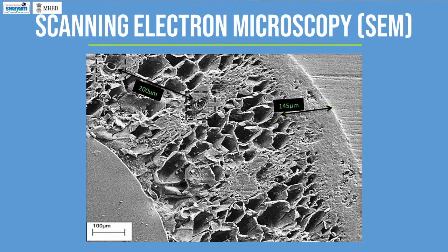this image. Elemental composition of wheat straw nodes by energy dispersive X-ray scanning electron microscopy showed different concentrations of silicon. It was found that the outer surface of the wheat straw had higher silicon content than the inner surface. The same study also revealed higher carbon content in the node outer surface, which is an indication of high quality of wax.